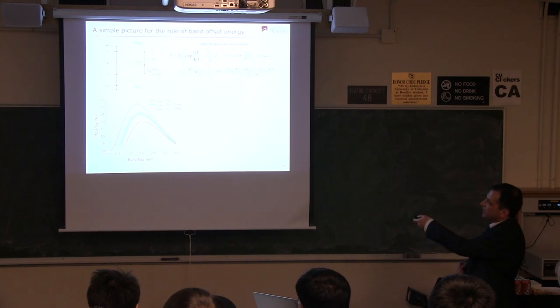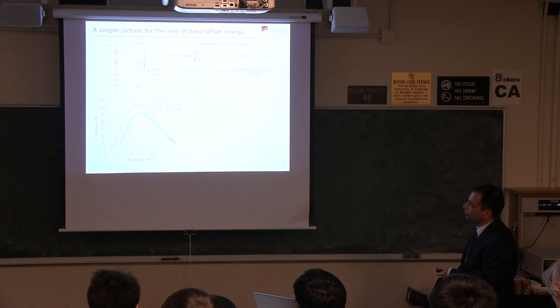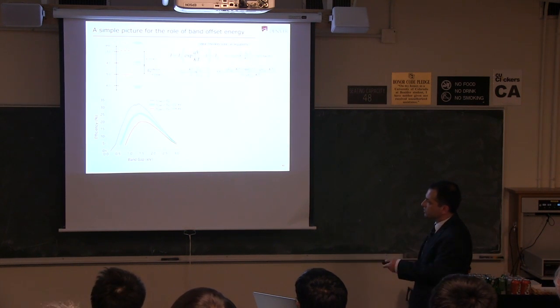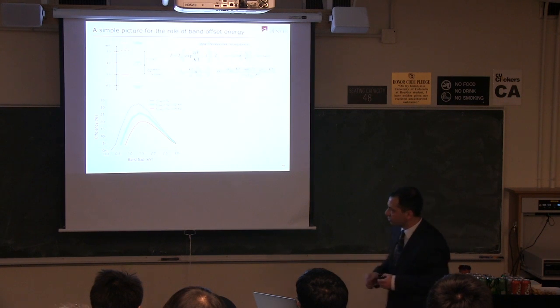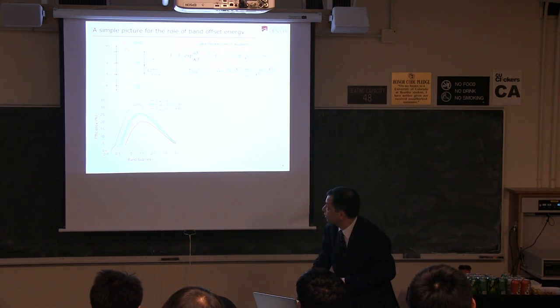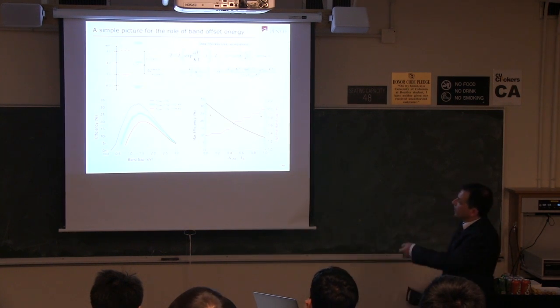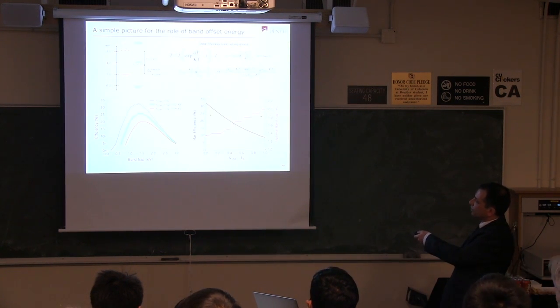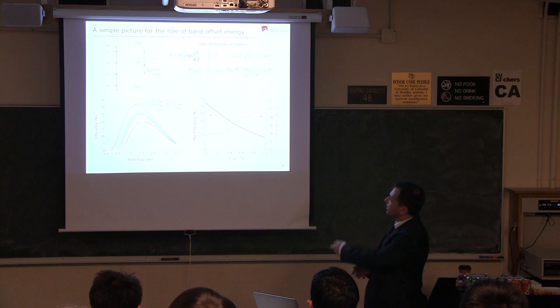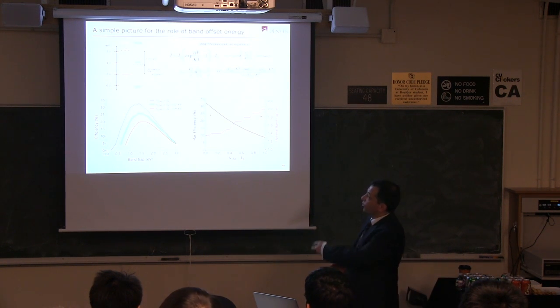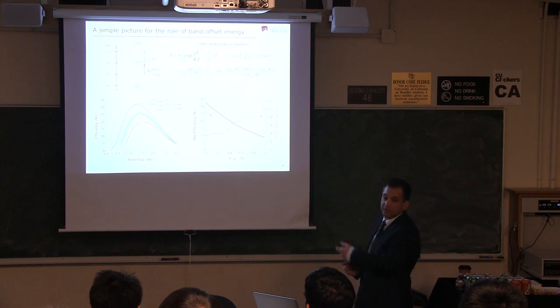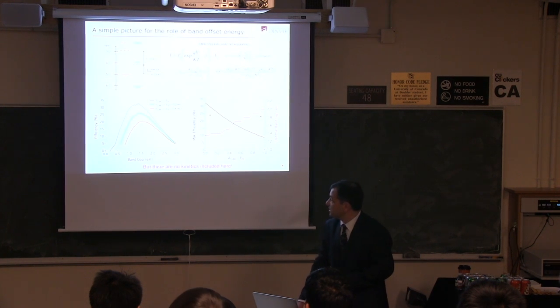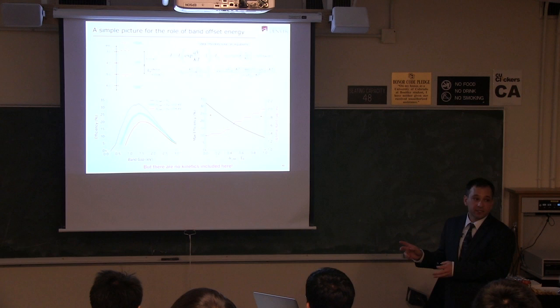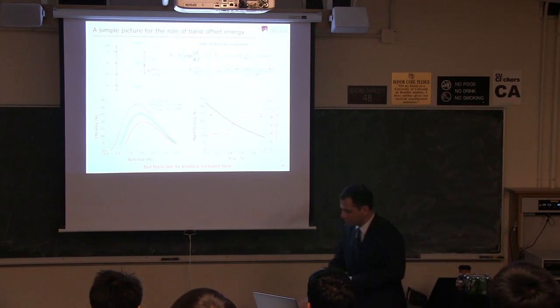As you increase the band offset, this number gets larger, and you wind up losing voltage in the device and shifting the maximum efficiency down, as well as the optimal band gap goes to higher energies. So by the way, if you plot optimal band gap versus the delta LUMO, then that number goes up. It goes from 1.4 all the way up potentially to 2 eV as the optimal band gap, but you've lost efficiency all the way down to 10%. Point is, we want to minimize this band offset as much as possible, get onto the blue curve, and get up to the 30% level. Now this picture is very simple. It's simply energetics. There's no kinetics here. It doesn't talk about the rates of charge creation or recombination.